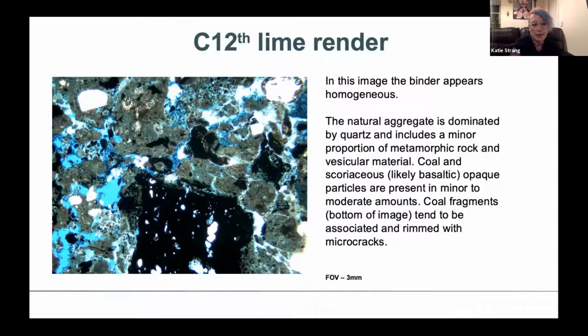Now, this fragment at the bottom is a coal fragment, and quite often, because the lime was burned locally, you would have a layer of coal, then a layer of limestone, and a layer of coal, and when they scooped the quicklime out, everything would just get chucked in and slaked together. So you end up with these particles of coal in there, but you also get other types of material as well. But the aggregate in this is predominantly quartz based.